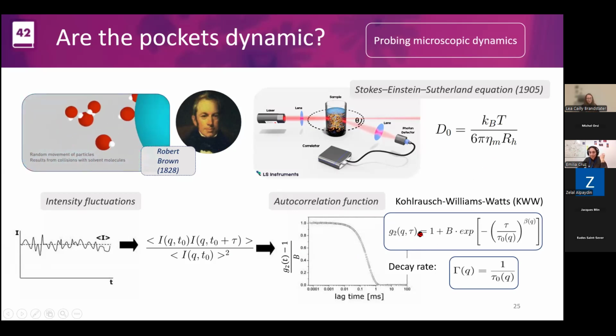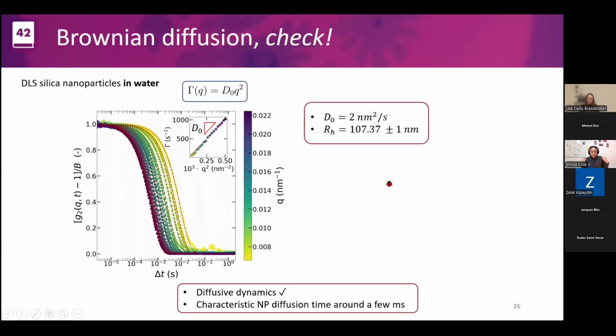Are they Brownian particles? This kind of experiment is very easily modeled with the Kohlrausch-Williams-Watts (KWW) model, which is given by this exponential decay, and it allows us to obtain this characteristic decay rate, which is given by 1 over a characteristic relaxation time. We're going to call this gamma of Q, and let's take a look at what happens if we put our particles in water. This is an experiment I did here in the lab: dynamic light scattering of silica nanoparticles in water. We put a few of these particles, irradiate with the laser like I showed, and see the intensity fluctuations. We get our autocorrelation function, and we see that there's a characteristic decay. Then we plot that characteristic decay for different angles, which allows us to scale the whole thing and obtain the slope.